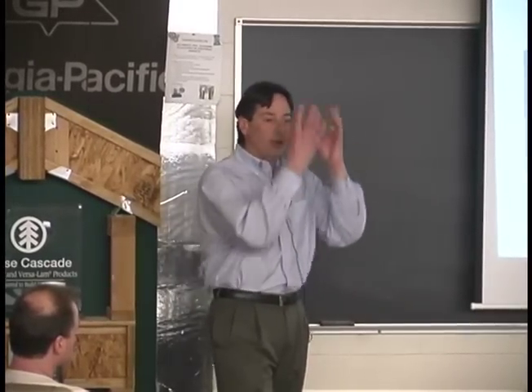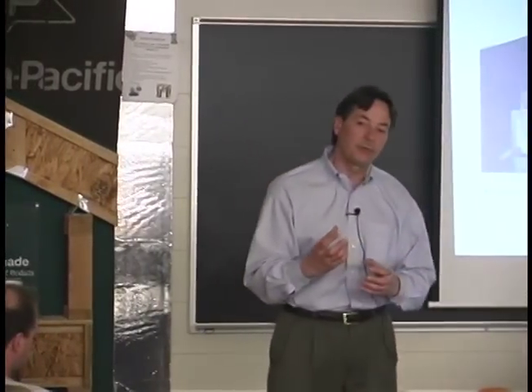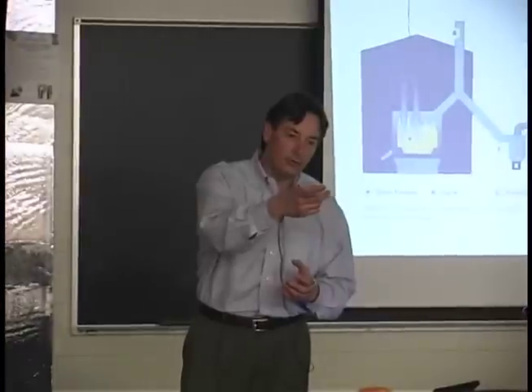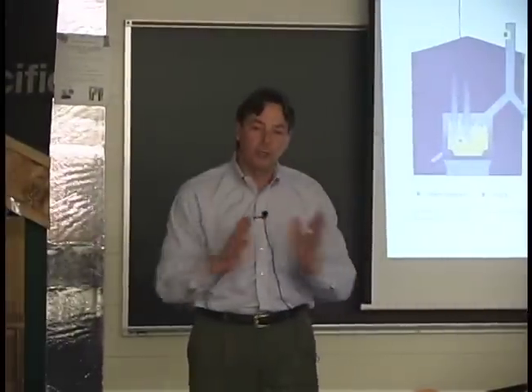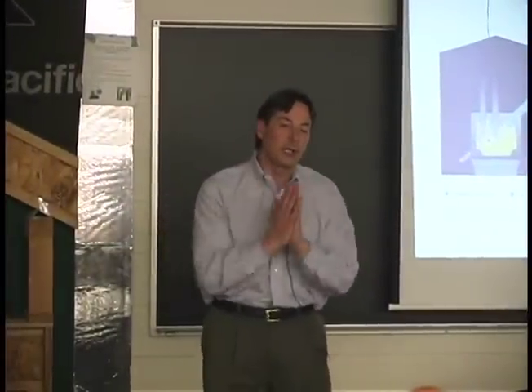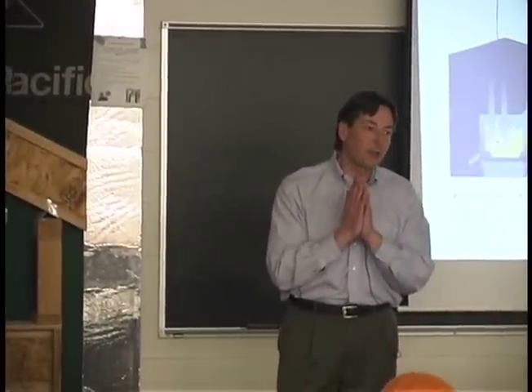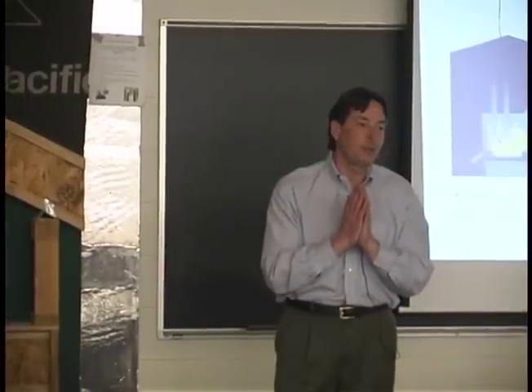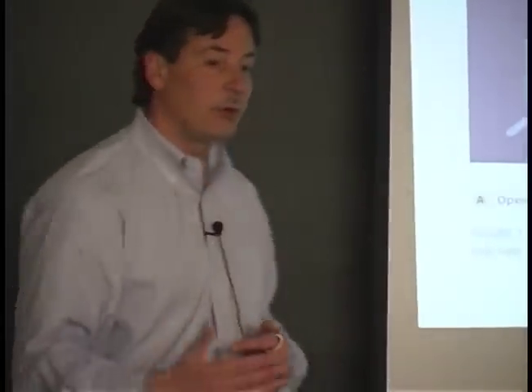It's just all kind of air coming up through the silo. What happens is when the air goes through this column of silica fume, it causes those little particles to collide. And because of van der Waals forces, the attractions of fine particles, they actually start sticking together. And so we can actually increase the bulk density of the silica fume from 8 pounds a cubic foot up to about 40.